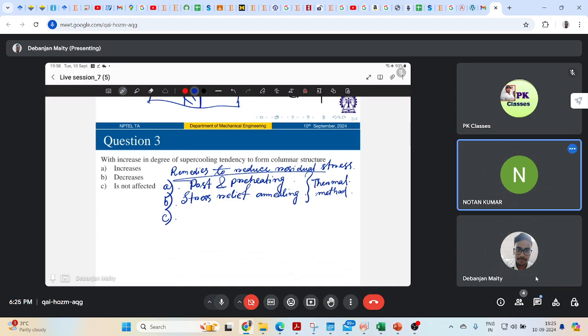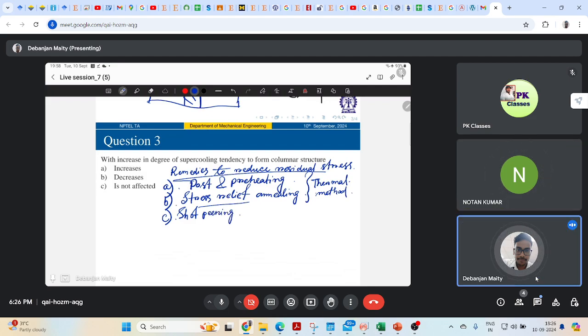You are asking what can be a mechanical method to reduce residual stress? Heat treatment is a thermal method: stress relief annealing, preheating, post weld heat treatment, tempering. These are thermal methods through which you can reduce residual stress. What can be some mechanical method? You must have heard of shot peening.